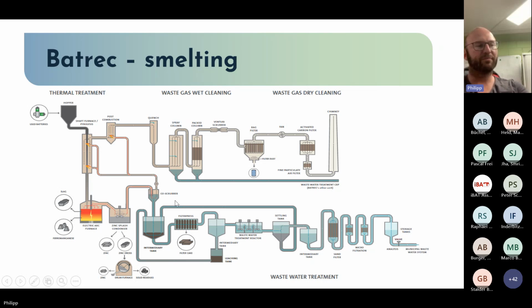Another advantage, what I mentioned before, is that we separated our wastewater lines. So we do a heavy metal precipitation here. We can bring this to the filter press, and the filter press cake contains nearly no mercury. And that's the reason why we are able to recircle this filter press cake to our input material. And so we have an internal loop for this filter press cake because the content there is 30 to 40% of zinc. And this is something where we can increase our recycling efficiency.